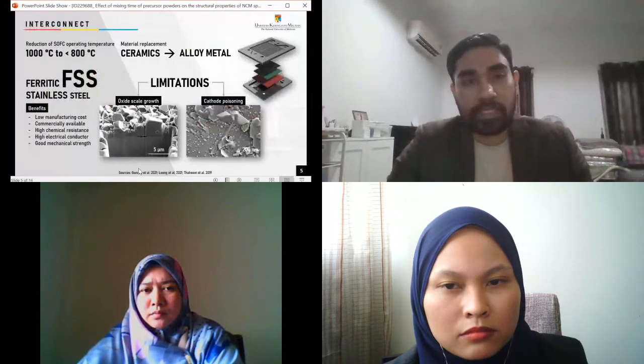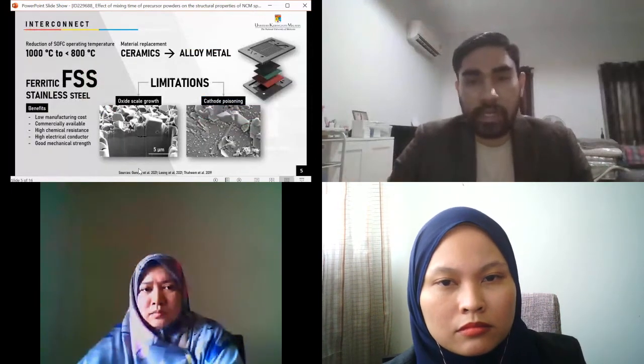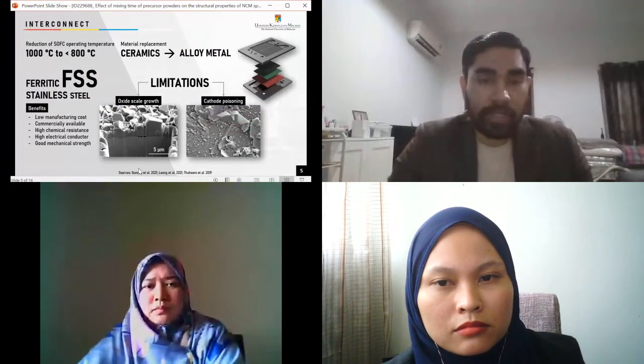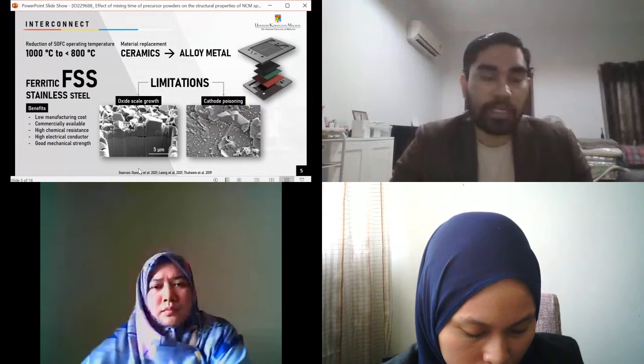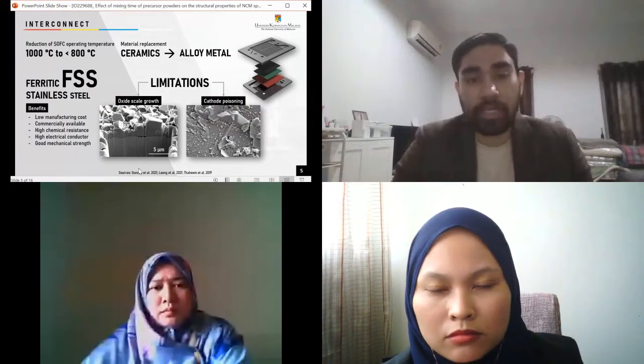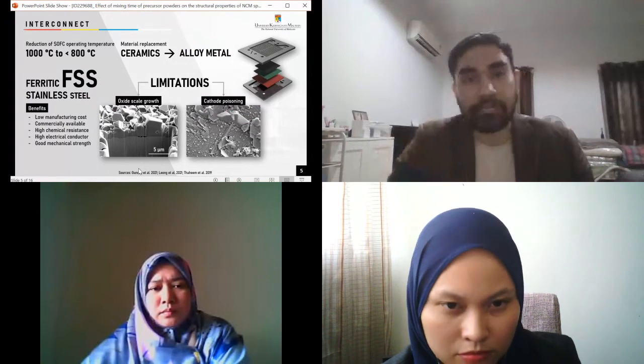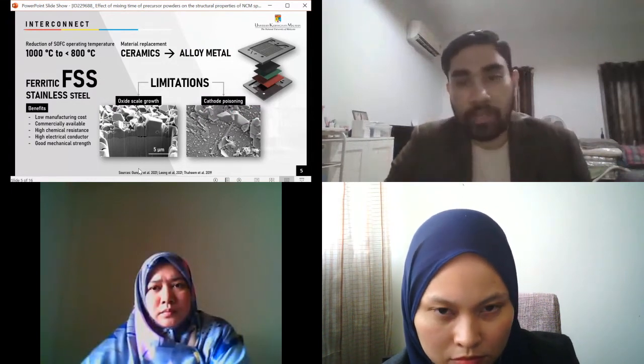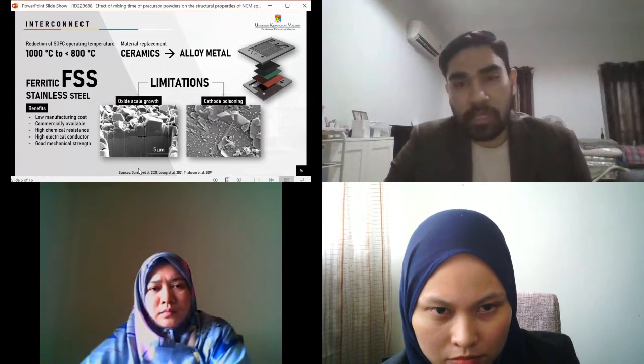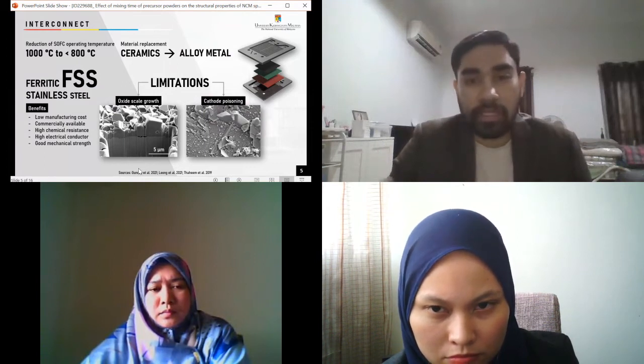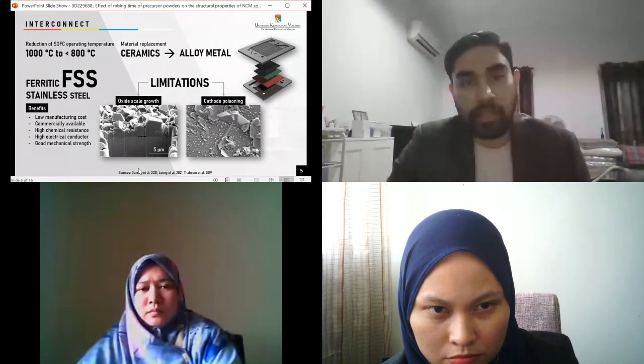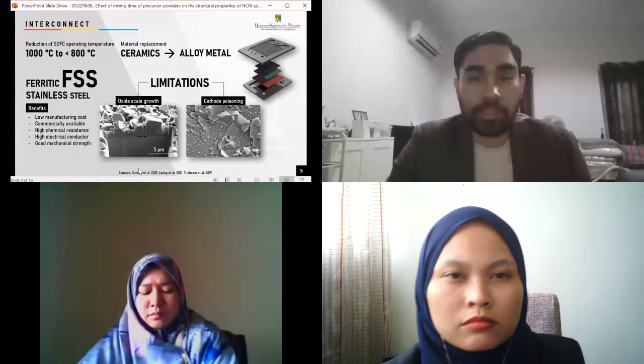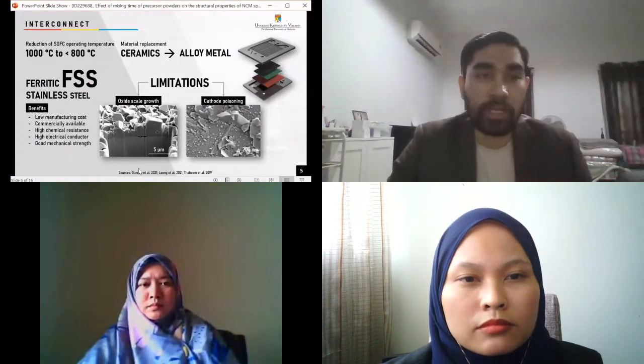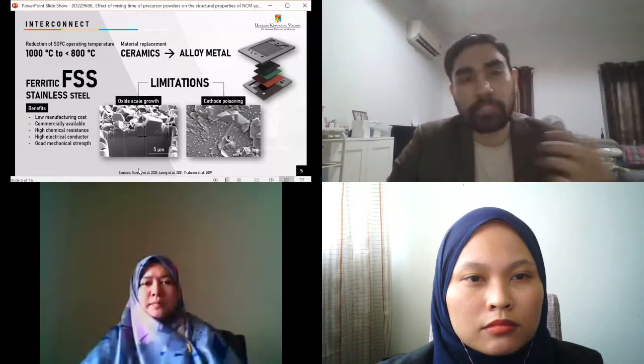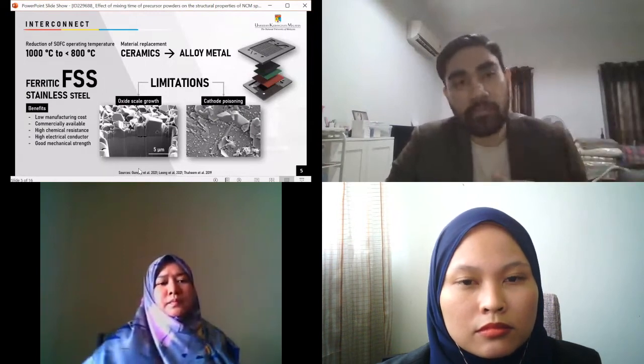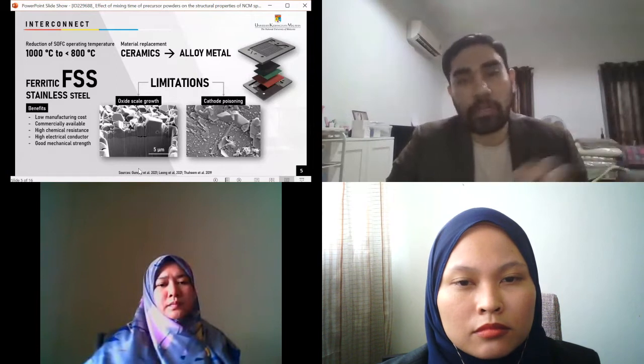So today I will discuss this particular component, which is the interconnect, and how to develop the interconnect further in order to increase the methane reforming inside the solid oxide fuel cells by applying a catalyst on the surface of the interconnect. So here, in developing the solid oxide fuel cells, recently more novel materials which have higher ionic conductivity were discovered, which allow the operating temperature of the solid oxide fuel cell to be reduced below 800 degrees Celsius. So this major breakthrough allows material replacement for the interconnect from ceramics to alloy metal.